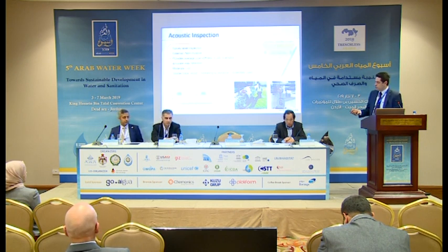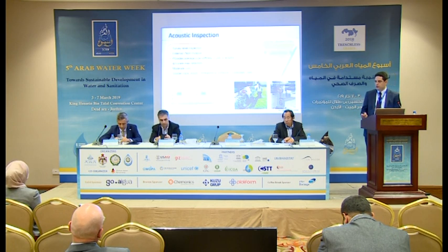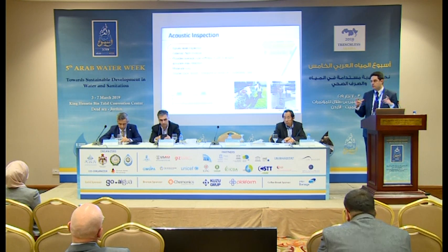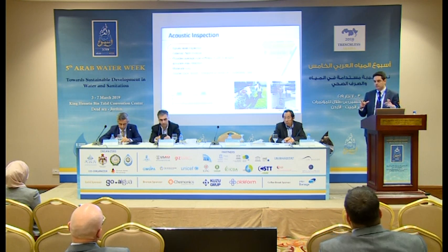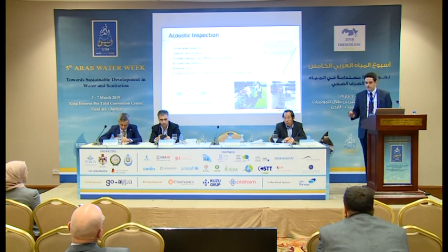And then a noise source is created outside the bracket of the sensors, and they measure the speed at which that acoustic wave travels from one sensor to the other. And using that information, we are able to calculate the average stiffness of the pipe, and then compare that stiffness to the stiffness of a good pipe. Based on that ratio, we can opine on whether within that segment there is a likelihood of a distressed pipe segment being